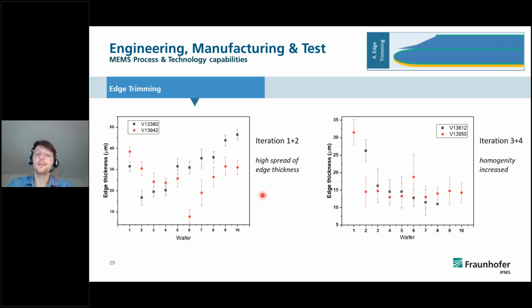Now there's a process step which we thought is a pretty common one and quite easy, but we actually faced the fact within the project that this is a very critical aspect also for later stage processing of those wafers, and this is the edge trimming. So what we basically did, we diced the top wafer in the profile that you can see here on the top, and diced it back from the edge of the wafer to the middle of the wafer with different steps. And you can see here the values that we tried to achieve.